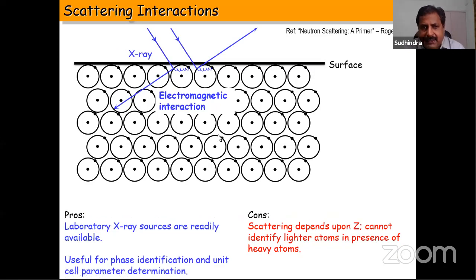The second probe which is widely used is X-ray diffraction. X-rays interact with matter through electromagnetic interaction, and because of that, they get scattered. The advantage of X-rays is that laboratory sources are readily available. There are very good commercial instruments, so you can do X-ray diffraction very routinely and easily. It is useful for phase identification and calculating unit cell parameters, because X-rays have very good resolution compared to neutrons. But the problem with X-rays is that the scattering depends on the atomic number. So you cannot identify lighter elements in the presence of heavier atoms. That is one of the constraints with X-rays.